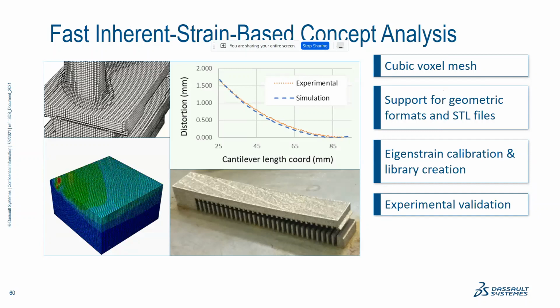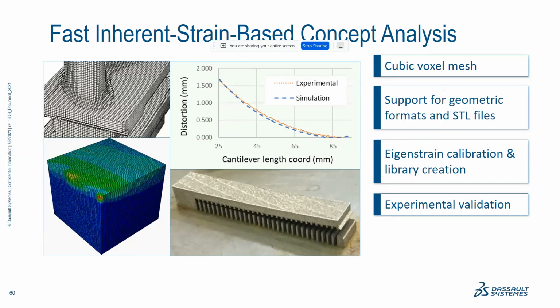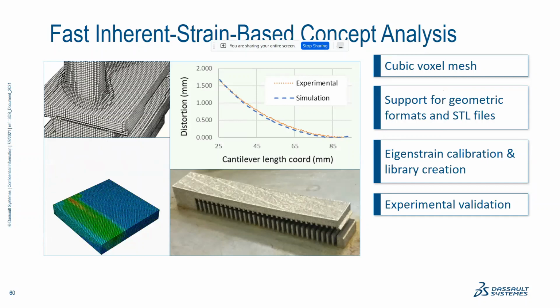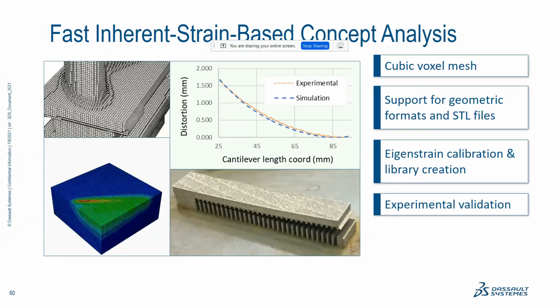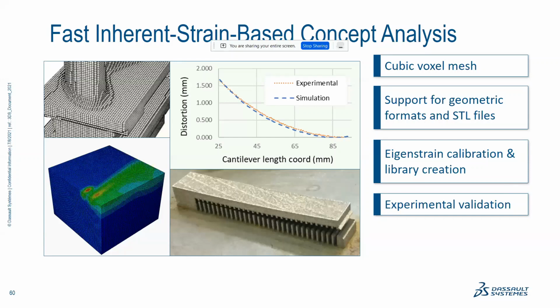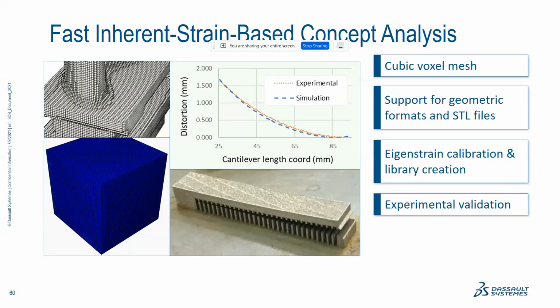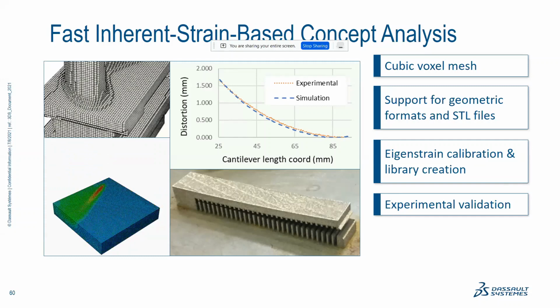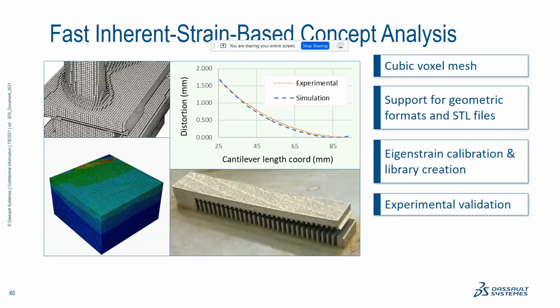So basically, in the fast strain method, which is a designer level tool, we are more meshing it with some cubic voxel mesh, which doesn't completely capture the surface in all smoothness. So in the earlier thermal structural analysis, we mesh it using tetrahedron mesh, which can give you good structure representation. In the case of fast strain method, there is some approximation, but we are still able to get a reasonably good, depending on how good the eigenstrain library is.